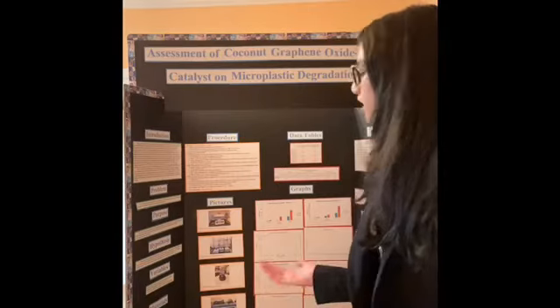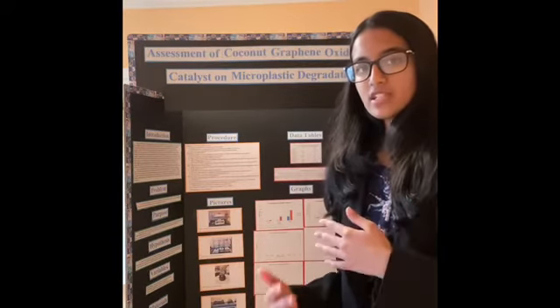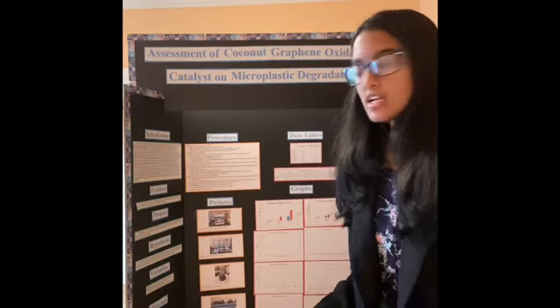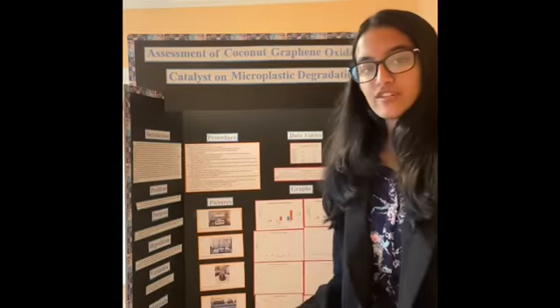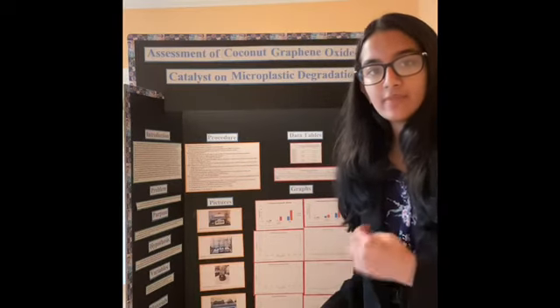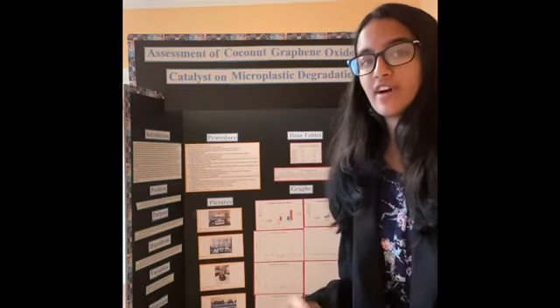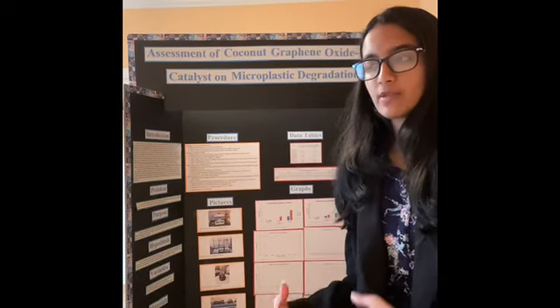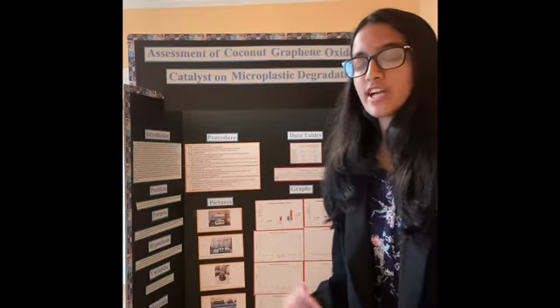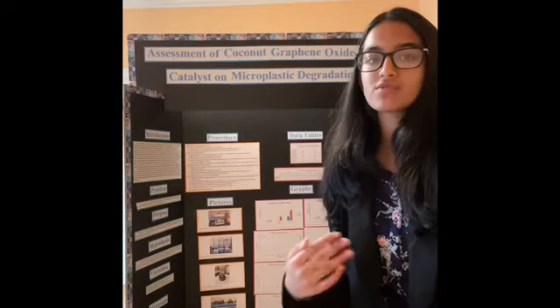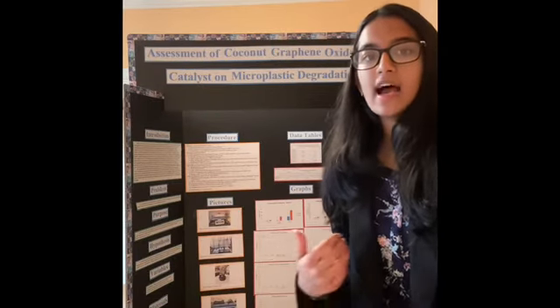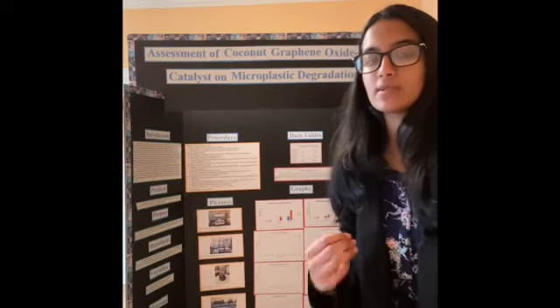With the FTIR, I found that through the peaks, these substances were formed, and I also found that for the coconut graphene oxide, there weren't very defined peaks, but after more research, I found that what was actually made was reduced coconut graphene oxide, which actually helped my project more because reduced coconut graphene oxide has fewer oxygen groups in it, which helps it become more stable.